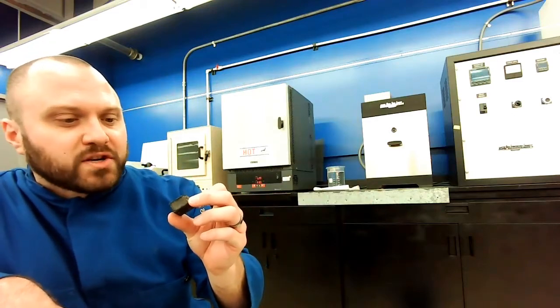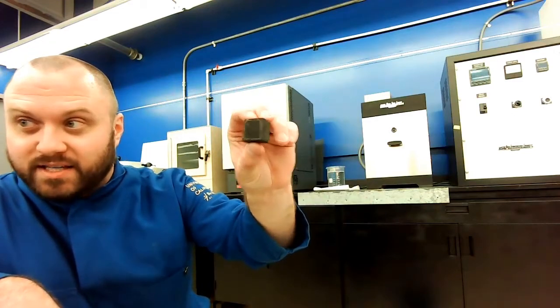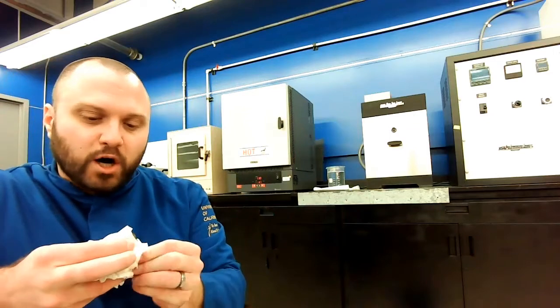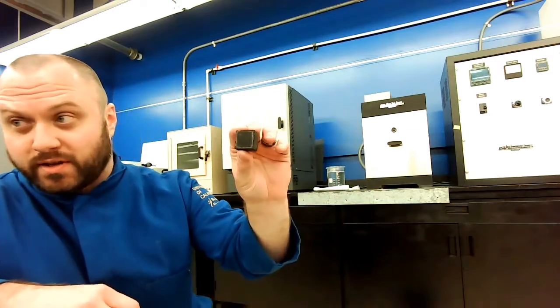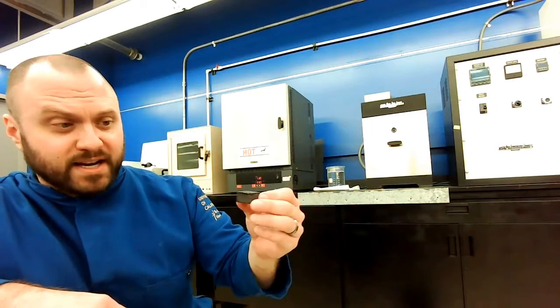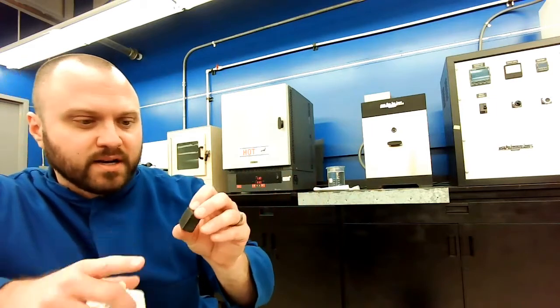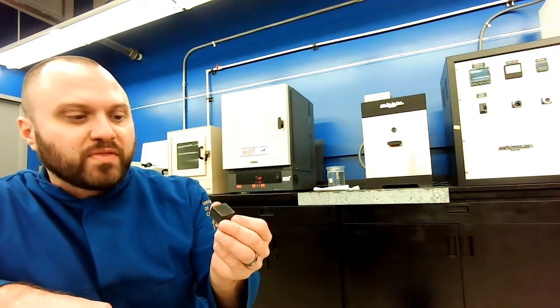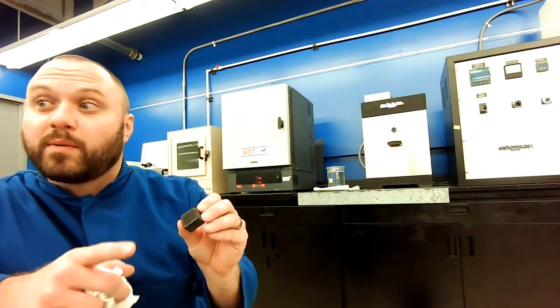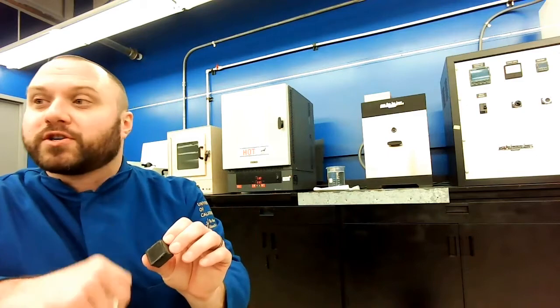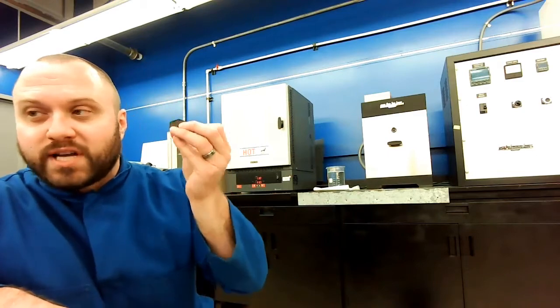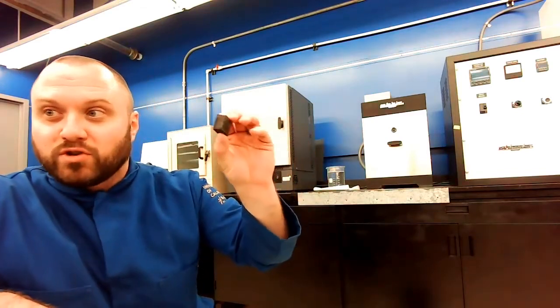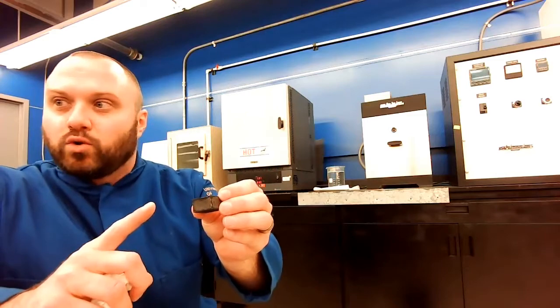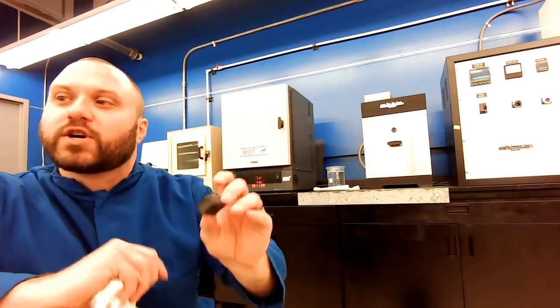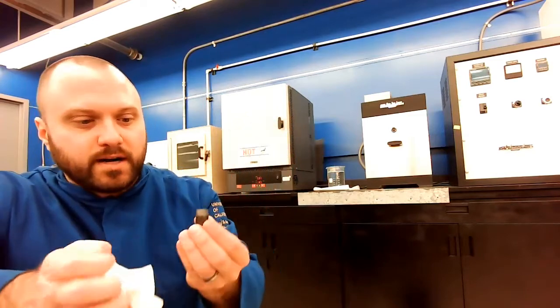But anyways, what we're gonna have to do is go and polish back, take this material off before we go and look at that surface and measure the surface properties. So we'll actually end up doing that next week. I'll show you how we can take that off. One thing we're gonna do is we wanna take that surface material off, but we wanna stay relatively close to that original surface, okay? So remember, we're taking this block that's really hot, putting it into a bucket of water. This block won't uniformly cool down. The outside is going to cool down faster than the middle, okay? So we're going to try to make sure we look at the outside of the structure, right?